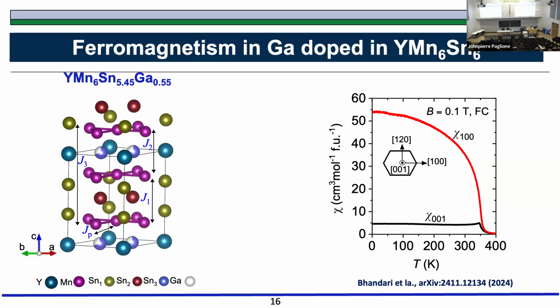And why would you care about making something a ferromagnet? This was very important to us. Although the ferromagnetic property itself is not interesting, there were some properties associated with the anomalous Hall effect, where it was claimed that it is because of the Chern gap or something in one of the compounds that has these ferromagnetic interactions in one of these 1,6,6 compounds. And when we were studying, we were not getting that. So making this compound a ferromagnet actually allowed us to test that. I'm not going to talk about that, but it was important. At least it was very important for us to get ferromagnetism in this compound.